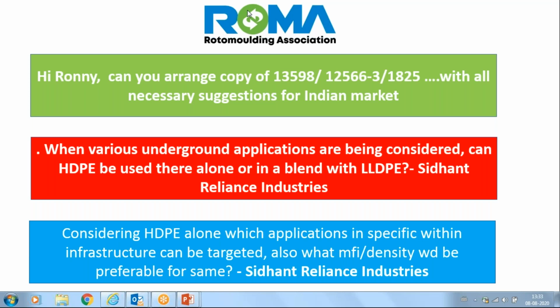What matters if you are producing small items is that you have the correct powder, that the powder distribution and the shape of the powder and so on are good. If that is not good, you will struggle to make good products, especially on the technical smaller items. But if you have a good powder, no problems. You will have a longer cycle time, of course, to collapse the bubbles with a low MFR than with a high MFR. But you can make any product you want with a good material for underground applications.